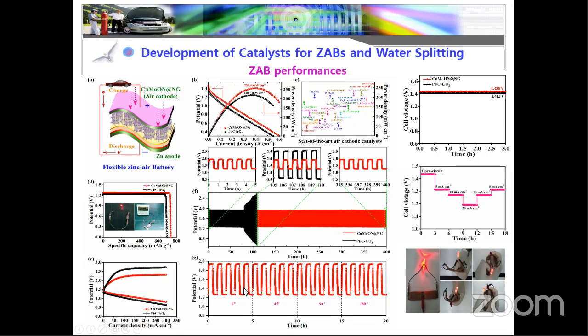The flexibility test was also confirmed with different bending tests, and we are also glowing a light at different bending angles. The rate capability performance was also confirmed by the long-term durability, the long-term stability in the discharging current.